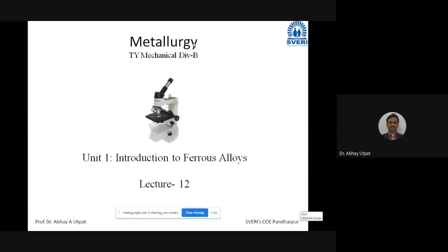If you check any of the cast iron available in nature, you'll find 4% to 5% maximum. Even 6.67 is the range, but at 6.67%, the cementite is 100% and it will be brittle. That's why in today's life, up to 6.67 is not taken.